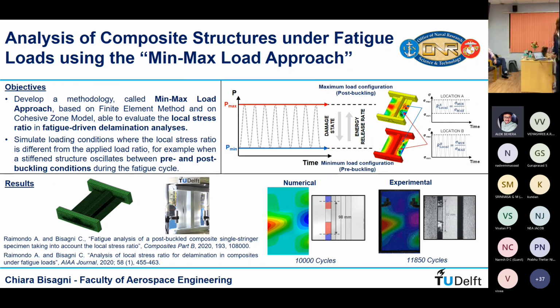But the problem is that if you test in fatigue, you have an area of skin-stringer separation, and this area is, in fatigue, very connected to what happens locally. So all finite element codes up to now introduce the global load ratio for the fatigue, which is the ratio that you apply in fatigue. If you think about a test in tension, it works well because you apply maximum load, minimum load, maximum load, and minimum load, and what happens locally is the same as the load that you apply globally.